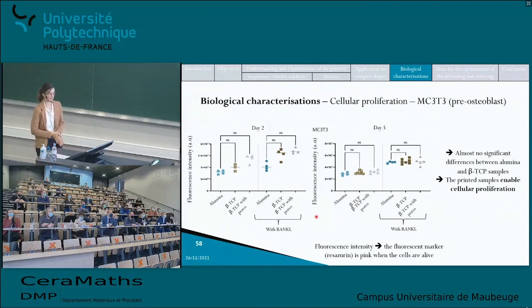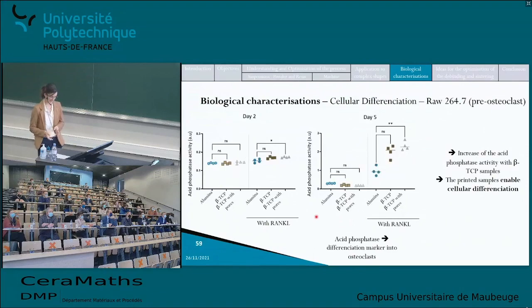The next step was the evaluation of the cellular differentiation. So I only presented one of the 5 tests that have been done, because actually 4 of the 5 tests gave the same results. So this is where the RANKL is useful to evaluate the cellular differentiation. So the acid phosphatase activity is measured, which is a differentiation marker for osteoclasts. So the goal here is to see if the pre-osteoclasts were able to evolve into osteoclasts.